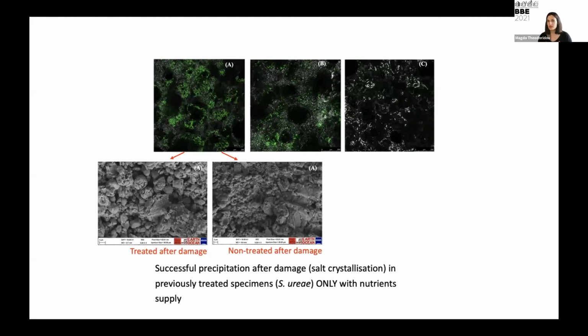And what is very important for the second healing stage is that here in the SEM pictures, you can see Group A specimens after damage that were treated with nutrients, where we can see new mineral formation, while in the Group A specimens that were only treated with water after damage, we didn't see that microstructure. So the results proved the successful precipitation of the damage in previously treated specimens only with further nutrient supply.